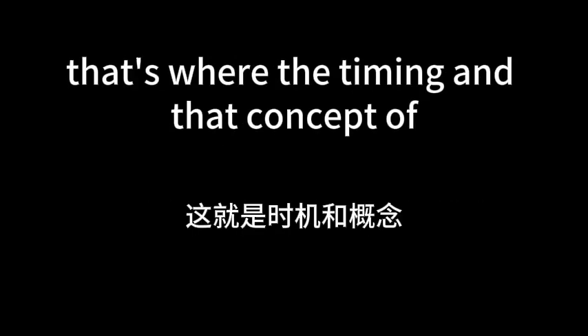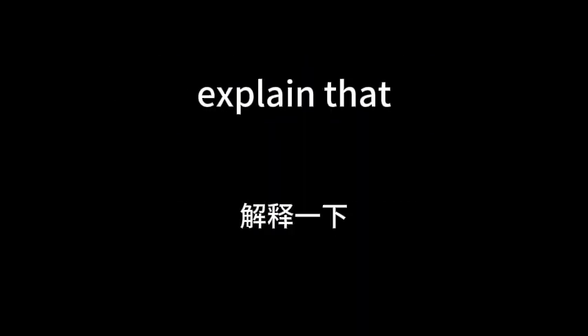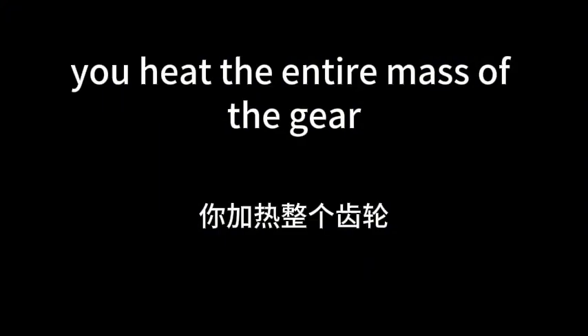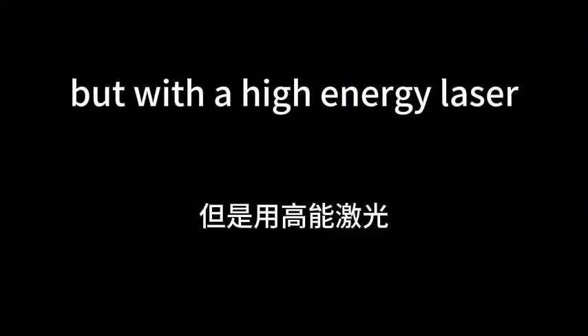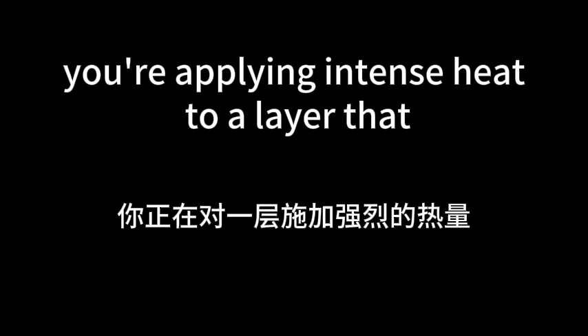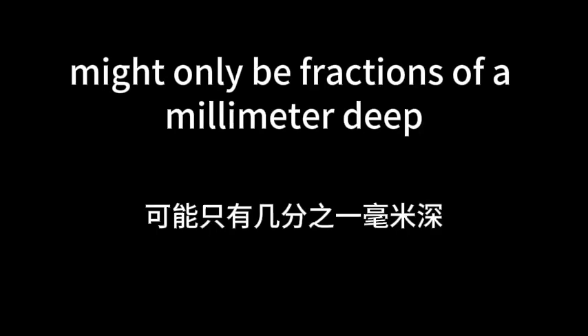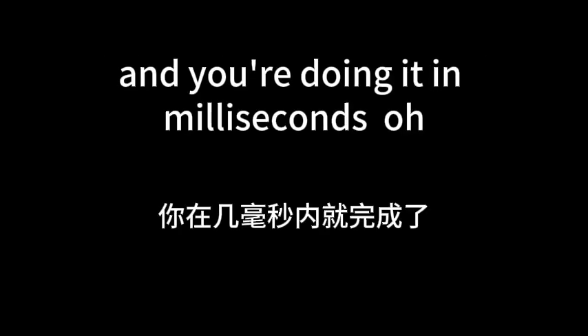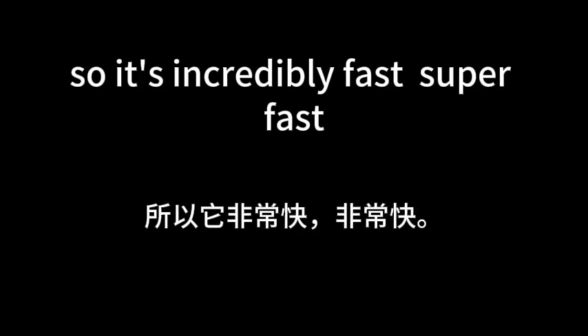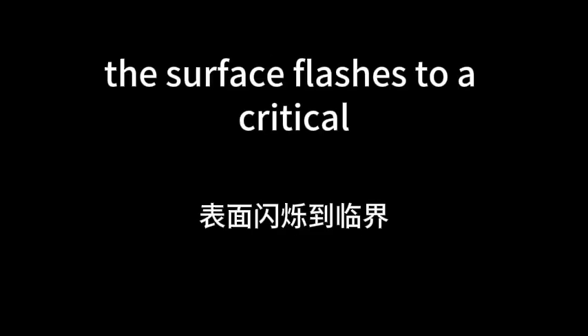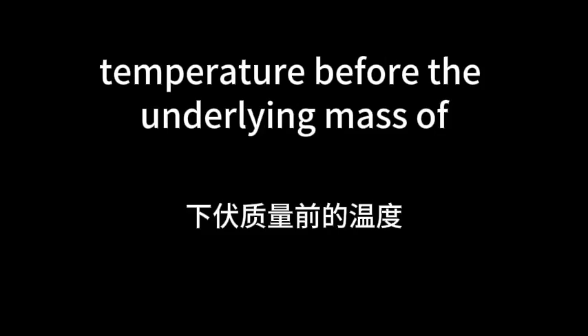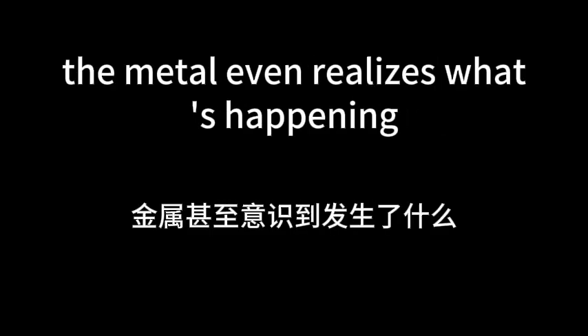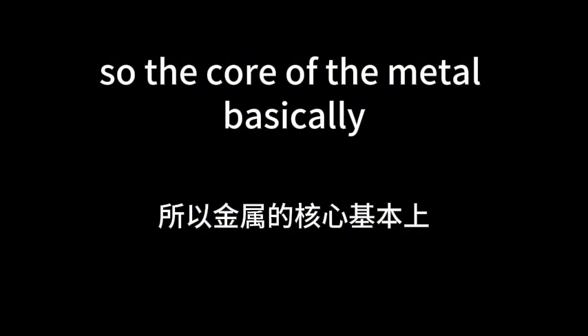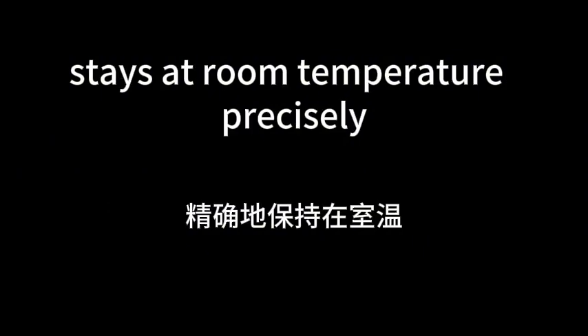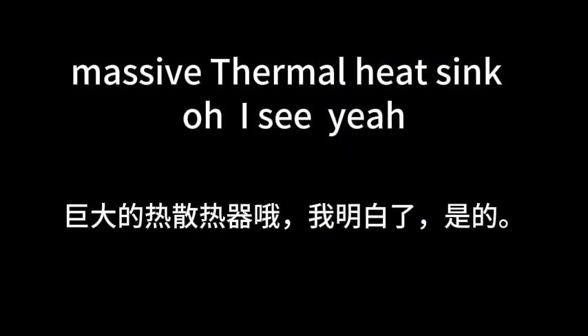Well, that's where the timing and that concept of self-cooling quenching becomes so critical. Okay, explain that. In a traditional furnace, you heat the entire mass of the gear. But with a high-energy laser, you're applying intense heat to a layer that might only be fractions of a millimeter deep. And you're doing it in milliseconds. Oh, so it's incredibly fast. Super fast. The surface flashes to a critical temperature before the underlying mass of the metal even realizes what's happening. So the core of the metal basically stays at room temperature. Precisely. And that cold core acts as a massive thermal heat sink.